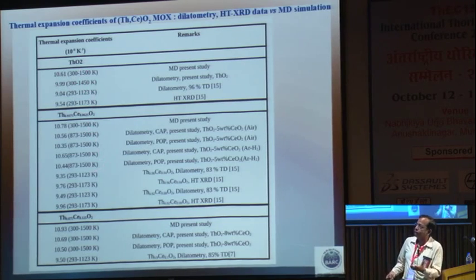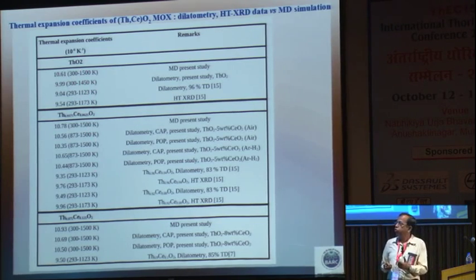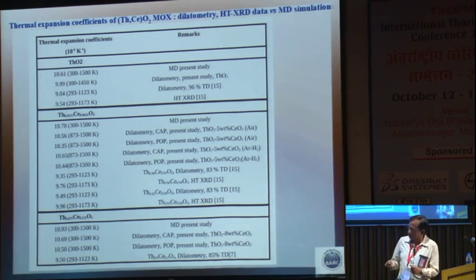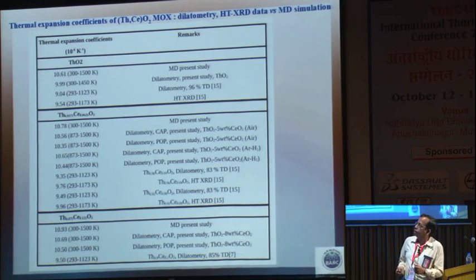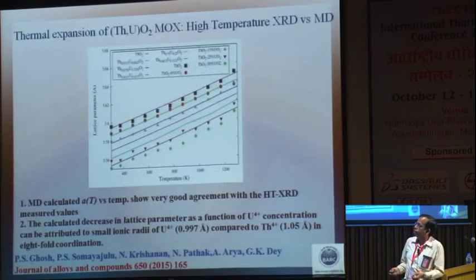So, it says that theoretical calculations can be used for predicting the behavior of mixed oxide fuels as far as thermal conductivity and thermal expansion results are concerned, and they can be used for modeling. This is for uranium oxide, where the experimental and the theoretical values are plotted on the same plot here, and again we can see that the agreement is very, very good. Here, instead of dilatometry, high temperature XRD has been used.